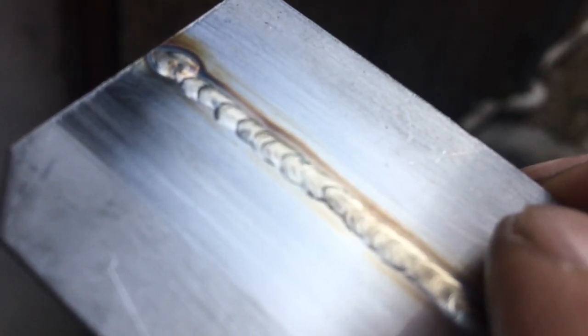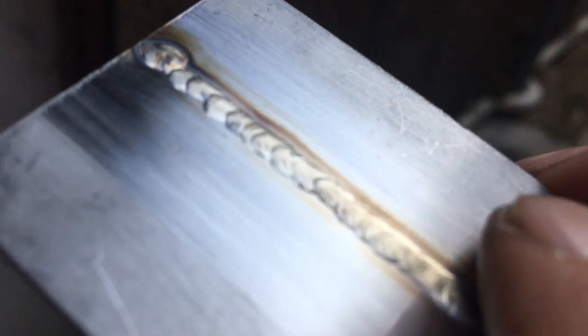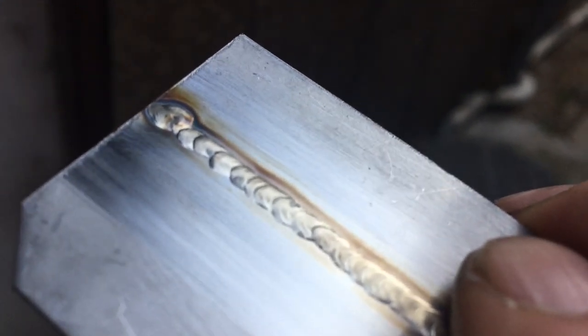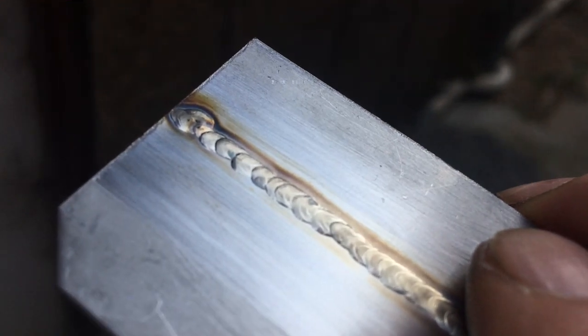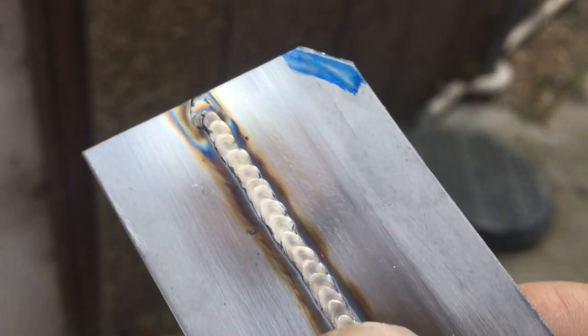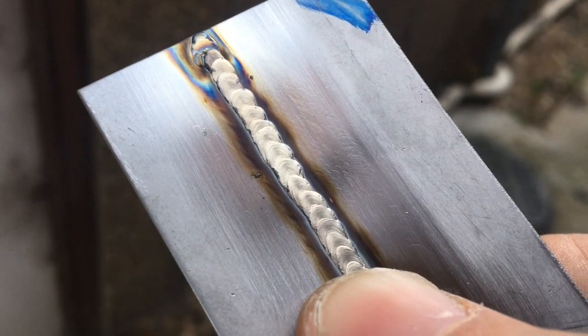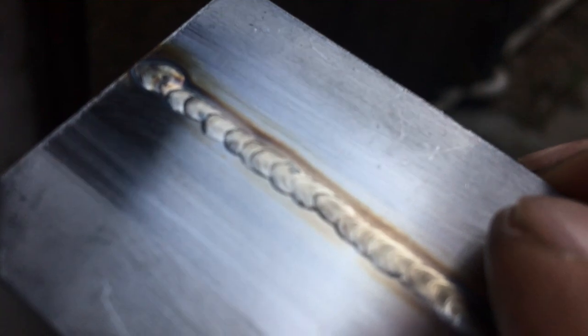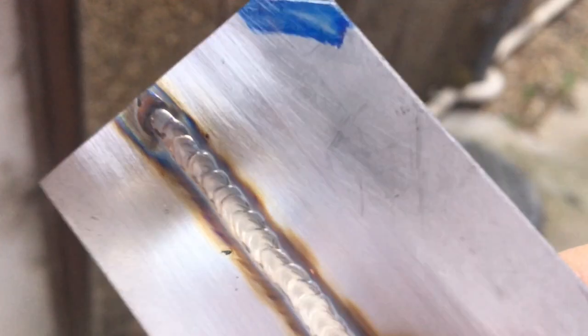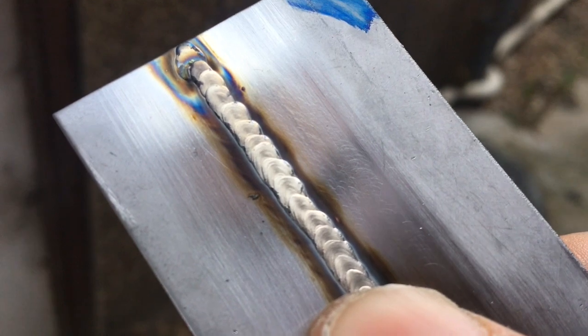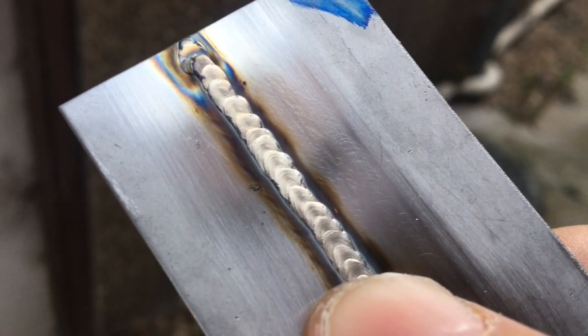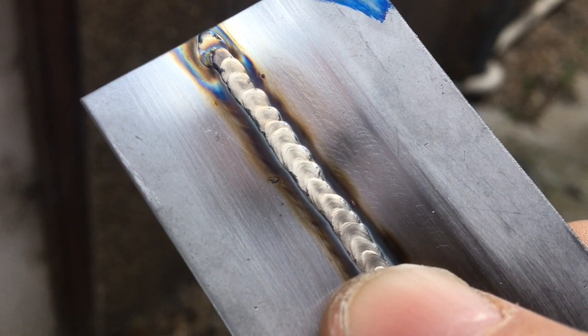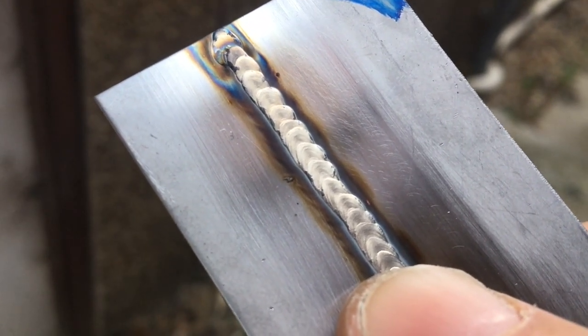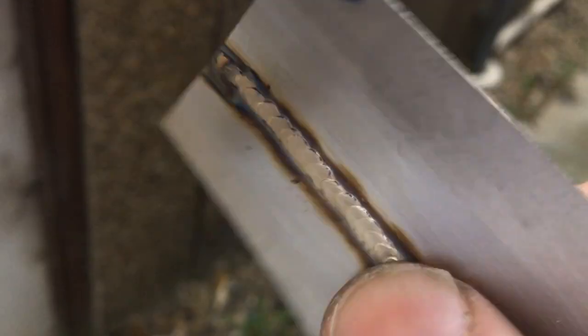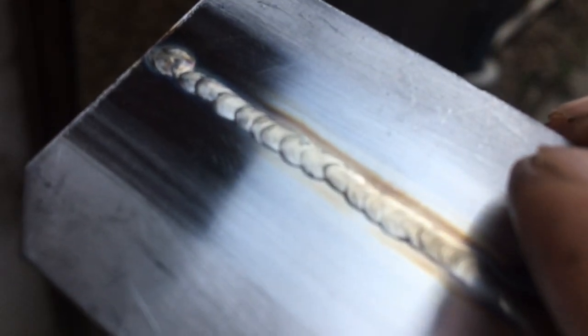Right, we're in the daylight now, it's a bit more forgiving. That's the back side of the weld. Silver, not oxidized due to the good gas coverage, reasonably smooth. And the top side of the weld, the side we welded, actually doesn't look too bad. I've seen worse, I've done worse, and that would probably pass your test. In fact, it has for me on many occasions. So it's closer to where we want to be. It's not beautiful, it's not Instagrammable, closer to where we want to be. So travel speed and cleanliness are the things that matter more with stainless than they do with carbon and alloy steels.